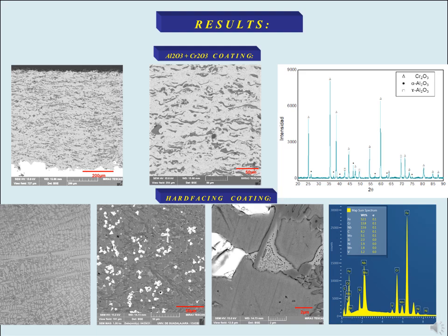Results. In the first picture, it can be seen the cross-section of the coating of 500 to 600 microns, and the second image is a high magnification of the first one, showing the combination of chromium oxide splats and the alumina splats. The white phase corresponds to the chromium oxide. The X-ray diffraction shows the presence of both phases. The lower picture shows the microstructure of the hard-facing coating deposited by welding. It can be seen the dendritic growth, and in the scanning electron image, a mixture of several phases. The microanalysis EDS shows the presence of iron, carbon, and carbide formers such as chromium, niobium, molybdenum, and so on. This is the typical microstructure of the hard-facing coating.